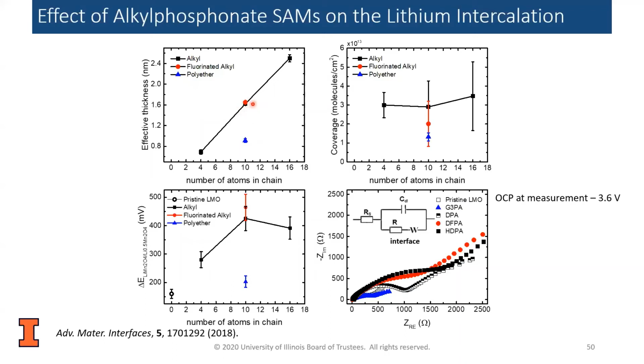We will notice though that the fluoroether, the fluorinated alkyl, has about the same thickness, which they were both 10 atom chains, well, actually it's a 10 atom chain, just like the 10 atom alkyl chain. But we'll notice that even though it has the same thickness as we expected, it didn't have the same coverage. And that's because the fluorine is a little bit bigger than the hydrogen. And so we had a little diminished coverage right here. So one thing we also noticed, which was echoed in the XPS spectra, is that the effective thickness of the polyether, as well as the coverage, were much lower than expected.